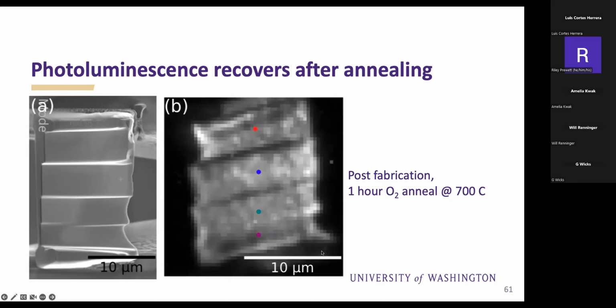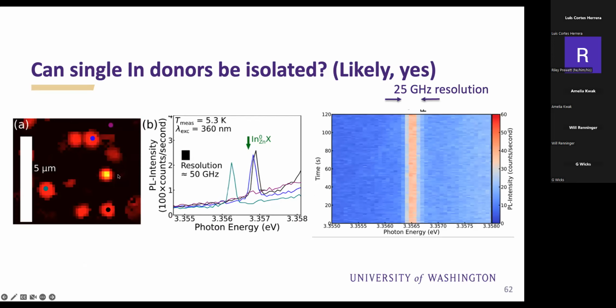This is the sample in our cryostat in photoluminescence, where we're collecting all the photoluminescence. And then if you filter on where the indium donor bound exciton line is, we can now observe the emission from single donors in this case. And within the resolution of our spectrometer, which is still too broad, you really have to do photoluminescence excitation experiments, but at least within the resolution of our spectrometer, we have resolution limited lines.